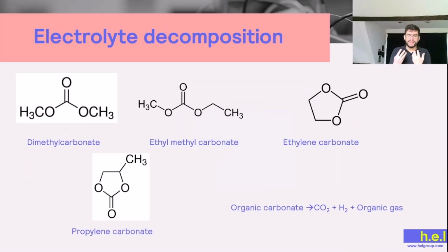So, what do decomposition reactions have to do with batteries? Normally the electrolytes that we use in lithium-ion batteries are going to be organic carbonates, such as dimethyl carbonate, ethyl methyl carbonate, ethylene carbonate, propylene carbonate, among others. The problem with these molecules is that if we expose them to high temperatures, they can break down, they can decompose, generating CO2, hydrogen gas, and organic gases such as methane, ethane, or propane that can be very flammable.